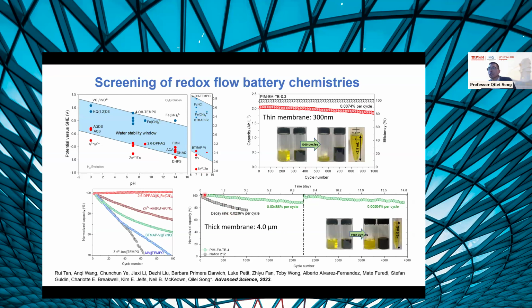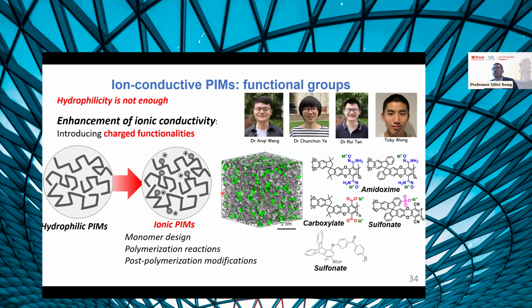You can see that there's a slow decay, because when we make the polymer into a thin film, the crossover of the species is still quite evident. So then we realized that the hydrophilicity of the polymer is not enough. We also need to enhance the ion conductivity and improve the selectivity. Following this work, we developed the ion conductive PIMs by incorporating these ion conductive groups into the polymers. This was a collaborative work, including several PhD students in my group, and also Chun Ye from University of Manchester. We were able to demonstrate this concept using several different PIM materials in collaboration with Professor Neil McKeown.